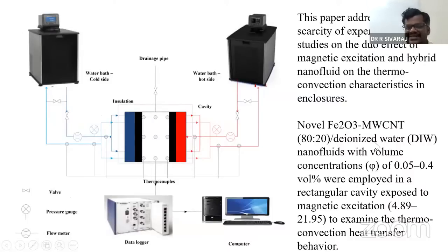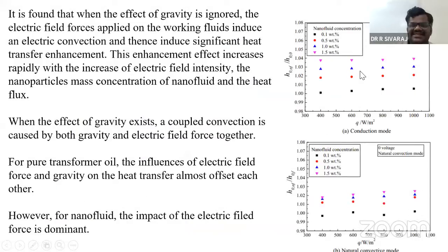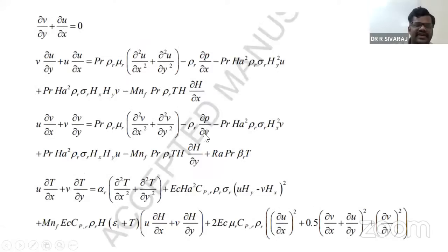Then the nanoparticle suspension is varied from 0.05 to 0.4%. We can also do that theoretically. Then the magnetic field is varied from 4.89 to 21.95, in terms of the Hartmann number, the pertinent parameter, and it can be analyzed. Here, as in the previous study, we have seen that there is a heat conduction mode or natural convection mode. Then the convective heat transfer can be accounted through this term. Whatever we physically see, through the expressions we can do that.